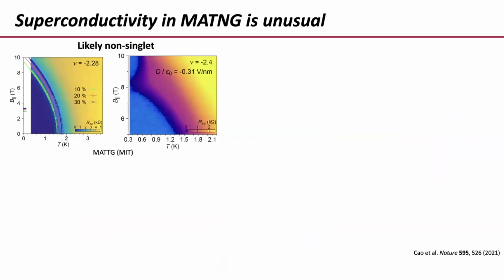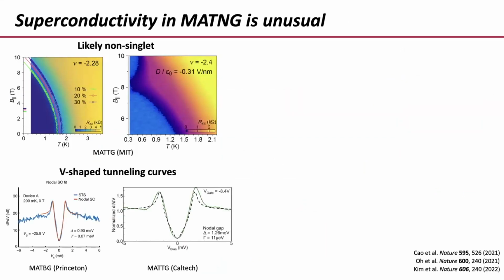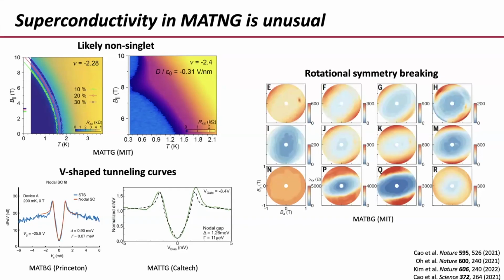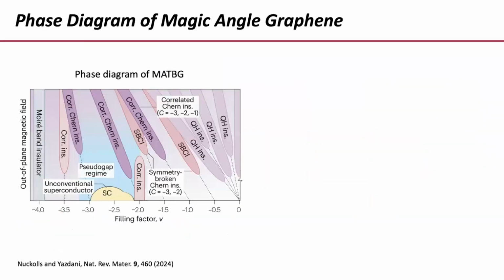And it's also unusual because it is likely non-singlet. The tunneling spectroscopy curves from experiments by Ali and by Stefan Nadj-Perge show these V-shaped tunneling curves. And it exhibits rotational symmetry breaking for some, depending on the symmetry properties also of the structure. So it's a pretty unusual superconductivity. And I would say it's a bit more mysterious than the topological properties so far, where theory and experiment have very quickly converged. Theory has predicted, experiment has demonstrated, experiment showed first, and then theory very quickly came and explained. Superconductivity is still a little bit mysterious.